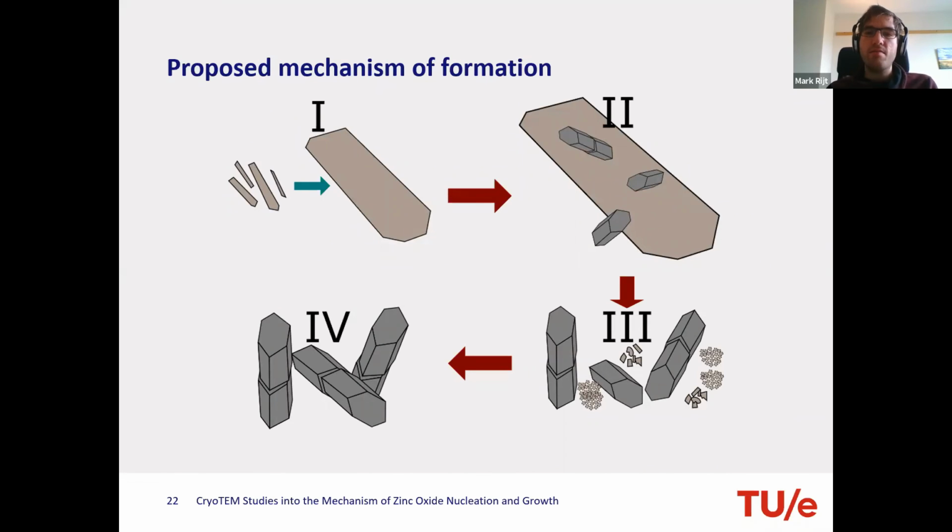So that suggests that we think that our layer basic zinc acetate crystals grow up to a certain point, and then because they start to introduce defects, they collapse. Because the crystals dissolve, this promotes the growth of all other present crystals in the solution, that's both layer basic zinc acetate and zinc oxide, which means that the other present layer basic zinc acetate sheets also grow above this point, introduce defects, until this whole phase in a very rapid time is consumed and we only have stable zinc oxide crystals left.